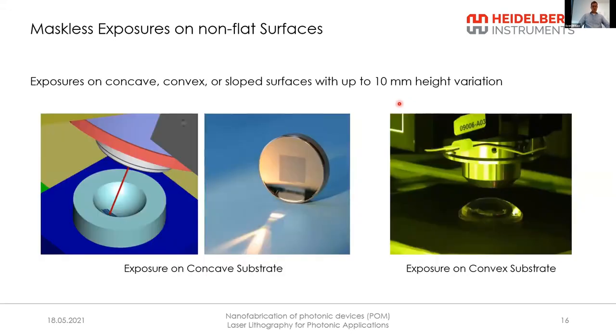You can do this even with thicker substrates. In this case, you can use substrates up to 10 millimeter in height variation, and this will allow you to expose, for example, on concave substrates to create features on this concave mirror. Or you can even write high-resolution features or micro lenses on these macroscopic lenses and combine microscopic and macroscopic optical elements.